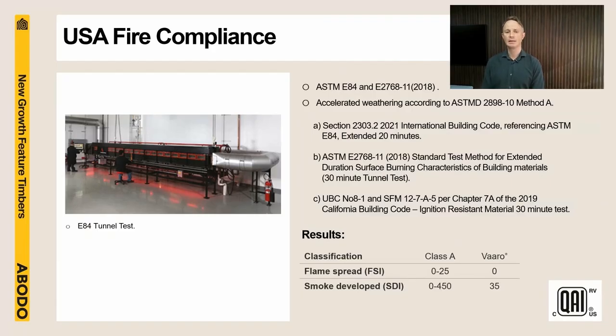For the USA, this country and market recognises a slightly different test method called the E84 tunnel test. And you can see here, this is a horizontal machine that has a 24-foot long wall section in it that then has a heat source introduced at one end. And in this testing, we did the 30-minute extended test that is recognised in the California WUI standards. And through this testing, we achieved Class A and with a flame spread index of 0. Again, this testing was conducted before and after pre-weathering at QAI in California.